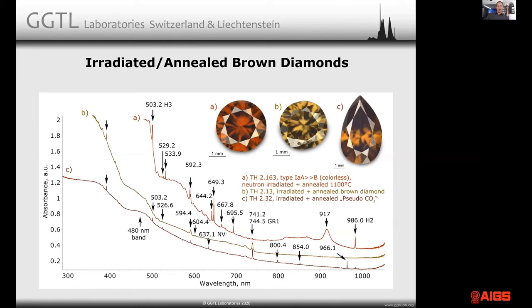These stones sometimes, or quite frequently, don't contain any significant quantities of nitrogen defects. The defects we see are not nitrogen related. So if you irradiate and anneal, you don't create the well-known nitrogen vacancy defect and all these things that change the color in a diamond by treatment. Hence, a CO2 diamond very frequently just doesn't change. It stays the way it looked before.